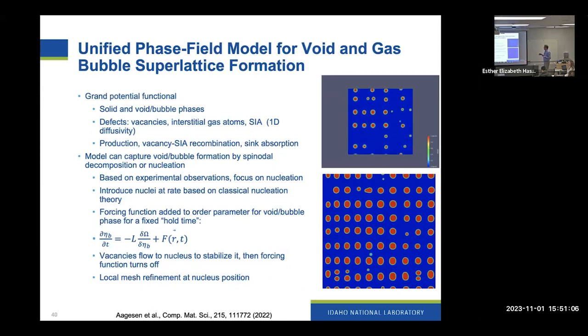We developed a unified model that could handle both of those types of superlattice. And again, using this grand potential functional approach, we incorporated vacancies, different types of interstitials that diffuse in different ways, and also gas atoms as well. And then again, accounted for the different types of recombination and sink absorption that can happen.